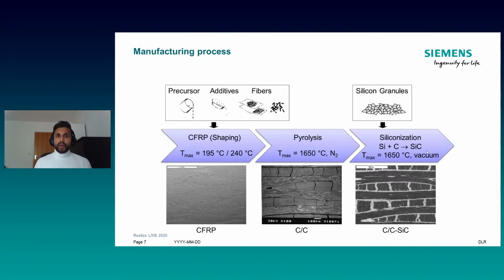Then we perform a pyrolysis step at temperatures of about 1650 degrees Celsius under inert atmospheric conditions to end up with a carbon-carbon material, where it's very porous in nature. You can see these black lines are pore channels, which are required in the next step, where we introduce molten silicon to form silicon carbide matrix. So what we end up with, the final material itself, is carbon fiber embedded in carbon matrix, a CC bundle, and then this CC bundle is embedded in a silicon carbide matrix.